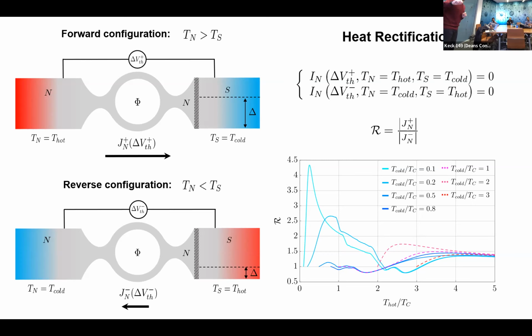Here, I have two families of curves: the blue ones and the reddish ones. The blue ones correspond to when T cold is smaller than the critical temperature, meaning that you're really exploiting the superconducting nature of the superconductor, while the reddish curves correspond to the temperature of the cold reservoir being bigger than the critical temperature, meaning that you're closing the gap. So you end up effectively with a normal system. You can say, well, okay, but in the case of a normal system you don't have the gap, you cannot break left-right symmetry. How is it possible that you get a rectification factor?